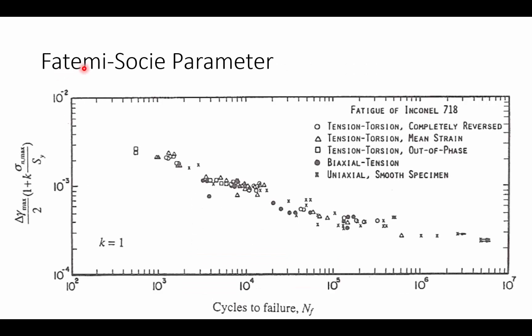When we apply the Fatemi-Socie parameter to experimental data, we produce a nice trend. The data coalesces on a single line, meaning the parameter as formed works well across many different types of multi-axial loading. This is key because it means this parameter can be used for many cases of multi-axial loading.